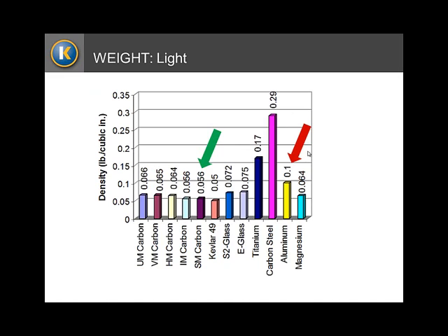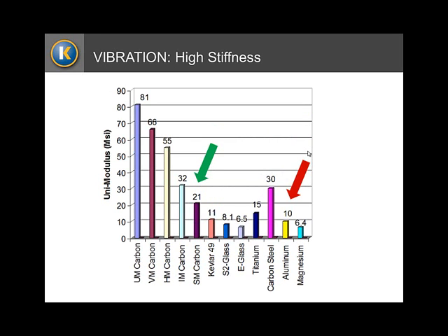Well, this chart here shows a comparison of the different types of composite materials. We've got carbon materials, there's various grades, Kevlar, fiberglass, S2 or E-glass here, compared to metals on the right. Now, aluminum is what the current incumbent base is made of, and its density is about 0.1 pounds per cubic inch, whereas any of the composites, you can see, E-glass all the way up to ultra-high modulus, are lower than that. In particular, standard modulus carbon is pretty good, and it's lower. So a good thing to do would be to just pick one of these composite materials to get the weight down. Well, it's not just about weight.